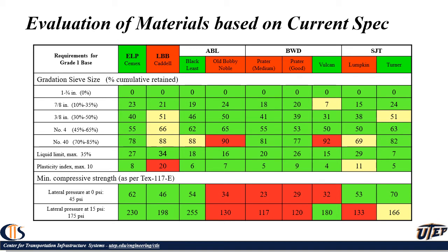These are the materials that we considered as an example over here. So we considered one material, called Cemex, that was all green. It means that it was passing all the specifications for a high quality base in Texas. And then a group of other materials from different areas, from quarries fairly close to each other, but some of them being considered higher quality than some of them lower quality. And again, you see that whatever is in red is just failing the specification, and whatever is in yellow is marginally passing or marginally failing the specification. So we have a good mix of different materials that we are considering.